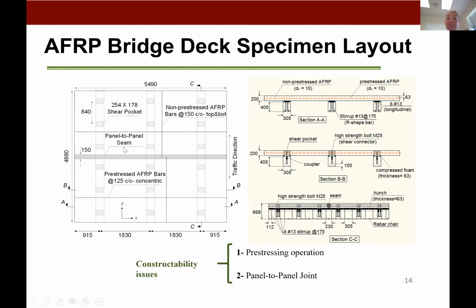And I'll talk about that because we wanted to make sure we had continuity of the shear transfer across the deck. We also had the same shear pockets as in the TxDOT case, where these shear pockets had these 10-inch by 7-inch pockets for which a high strength grout was poured in for these post-install anchorage to ensure composite action between the deck and the beams.